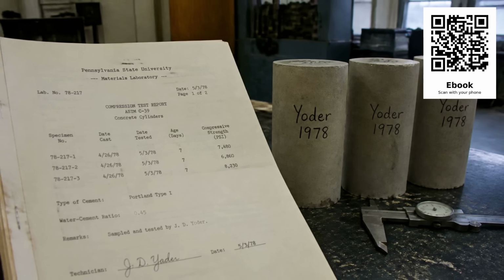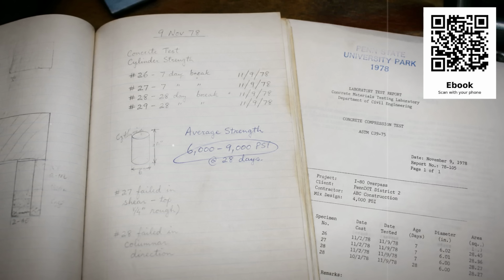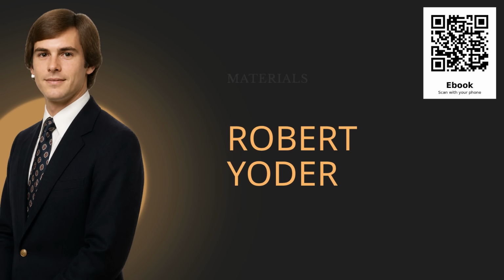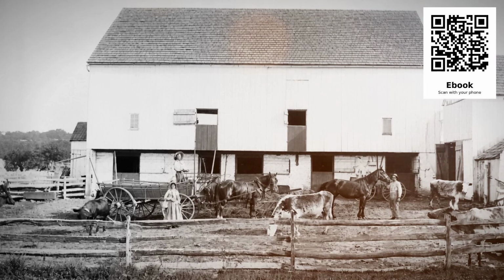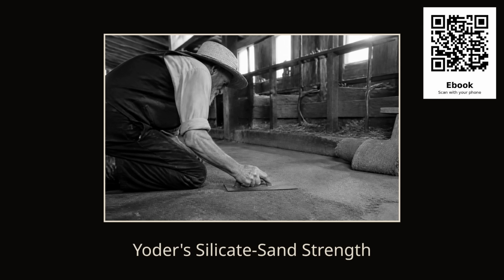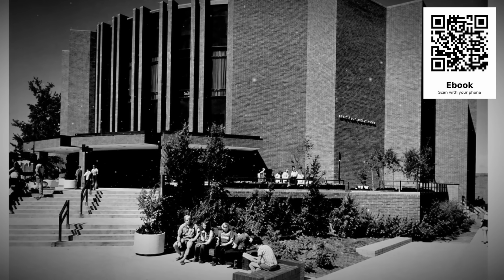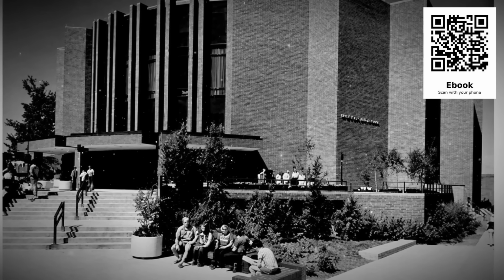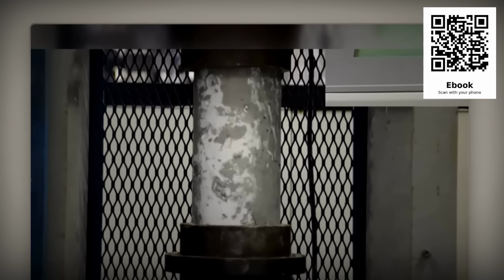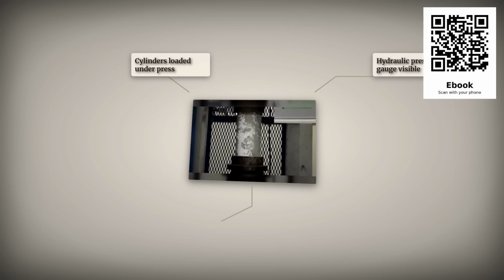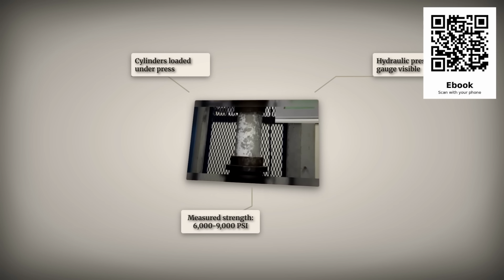The compressive strength numbers I gave you earlier, between 6,000 and 9,000 pounds per square inch, are from independent testing done at Pennsylvania State University in 1978 as part of a graduate thesis by a materials science student named Robert Yoder. Yoder, whose family was Mennonite, had grown up watching his grandfather pour silicate sand floors in dairy barns. He wanted to know, empirically, how strong the material actually was. He cast standard test cylinders using sand from 3 different sources, varied the silicate ratio across a range of mixed designs, and tested them to failure on a hydraulic press.